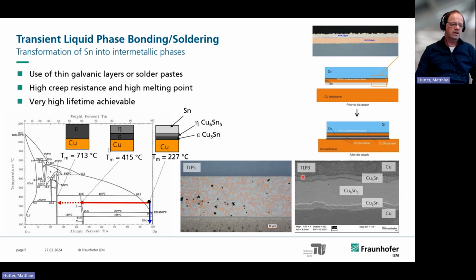Already during the soldering, everything transforms into intermetallic phases. You'll see this is 1 micrometer. It's only a few micrometers thick then. The good thing is you have then achieved a higher remelting point of more than 400 degrees Celsius. So you are beyond this line here, 415 degrees C.